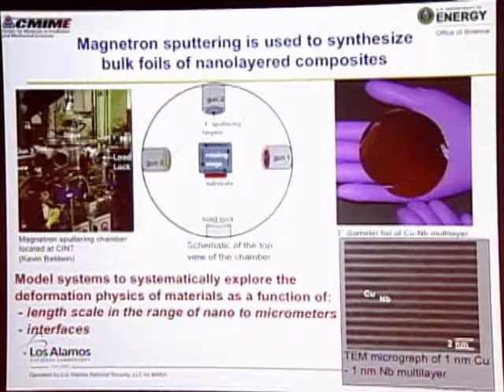So this is work that Kevin Baldwin does in his laboratory, where he uses a vapor deposition process called magnetron sputtering to make these bulk foils of nanocomposites. And so what he can do is he takes a substrate, a piece of silicon that he puts here, and then rotates the stage to one gun or another that deposits, say in this case, copper and niobium. So you'll rotate to gun 1, deposit copper, rotate to gun 2, do this with niobium, and then come back to gun 1 and do this over and over and over again until you build up a film that looks